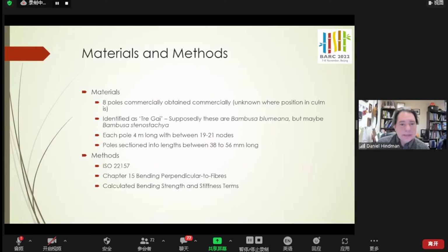So as I mentioned, we had 8 poles commercially obtained. We do believe they're Bambusa blumeana. However, this is one of the other problems with importing this material commercially. It may have been Bambusa stenostachya, 4 meter long. They had between 19 and 21 nodes in that 4 meter section. And we cut them into between 38 and 56 millimeter long pieces. So overall, we had something like 650 specimens.